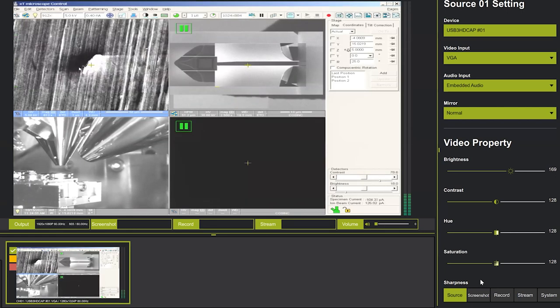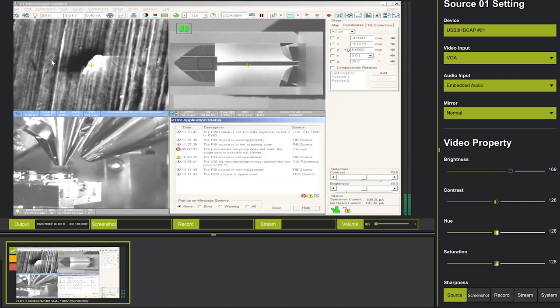This is the typical working environment. The working distance at the eucentric height should be about 5 millimeters for this instrument. So this is the electron beam pole piece. And this is the ion beam pole piece. Right now, I'm looking at the sample top down with the electron beam. For the milling environment, I wanna have the ion beam hitting perpendicular to the surface. Okay? So that means I have to tilt the stage. Tilt towards the ion beam? Yes. So I'm gonna tilt a smaller amount.